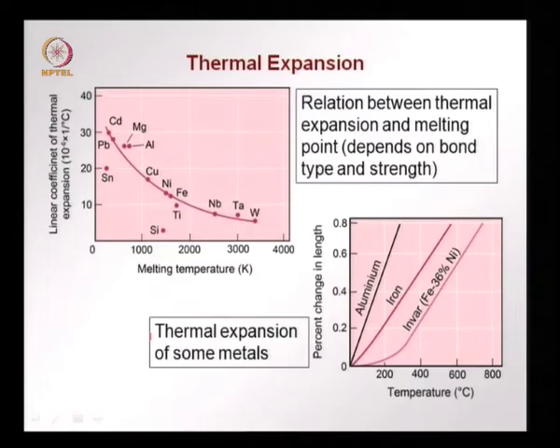Now, when we discussed the Condon-Morse diagram, if you remember, we said that when the bond strength is larger, the melting point is also higher, because the energy needed to break the bond is higher and this increases with the strength of the bond. We also saw that when the well was narrower and deeper, that is for a stronger bond, the narrower well width gave rise to less variation of the average interatomic spacing at different temperatures, that is, the thermal expansion was also less. So, when we have strong bonds, we have a higher melting point and we also have a lower thermal expansion, and this is what you see here on the curve on the left.